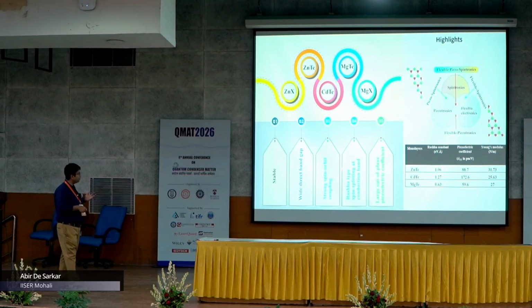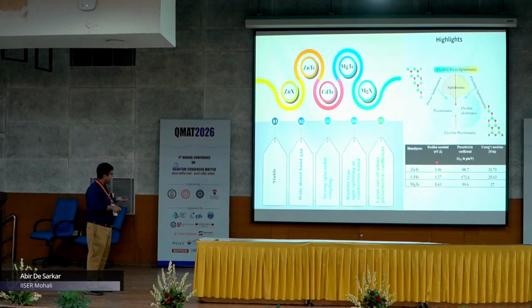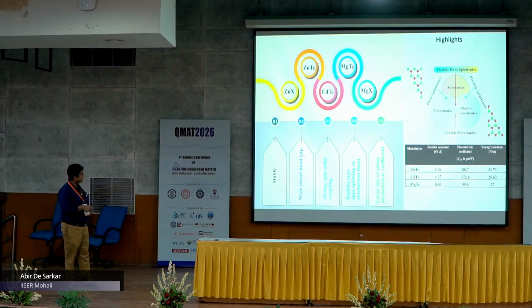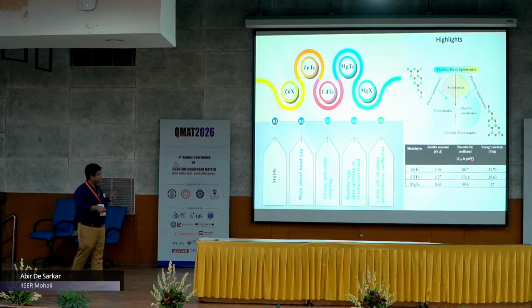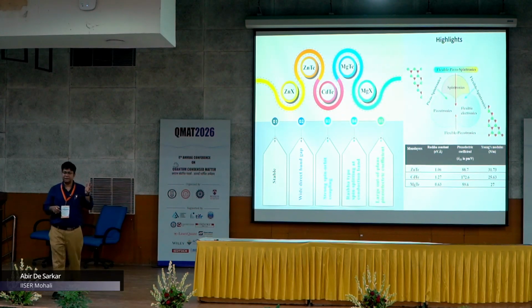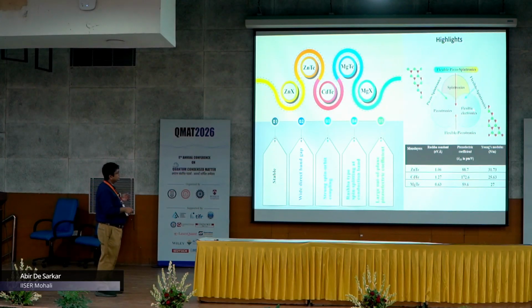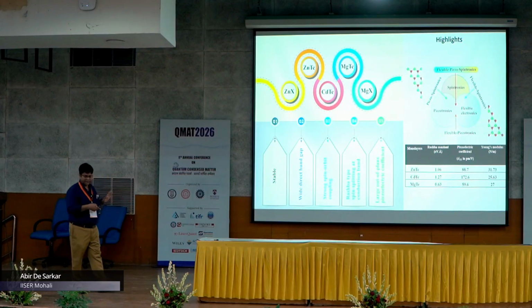So, in summary, we find that these three monolayers, CdTe, MgTe and ZnTe, are stable, have a wide direct band gap and a strong spin orbit coupling, which shows up as a reasonably high Rashba constant, or Rashba type spin splitting occurring at the conduction band. Since they exhibit a large Rashba constant, they satisfy this condition. And also, these monolayers show a reasonably high out of plane piezoelectric coefficient. So, they also meet this criterion. These three monolayers show small Young's modulus, so we understand that these monolayers are stretchable and flexible. So, this condition is also satisfied. Therefore, we propose that these three monolayers would be suitable for flexible piezo spintronics.